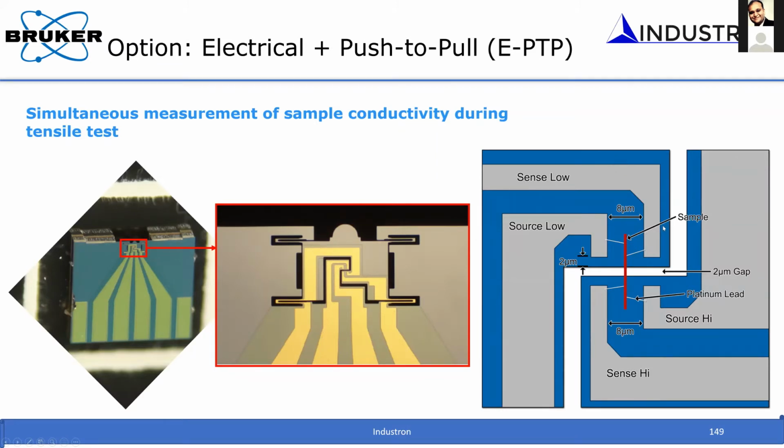For example, we have the PTP, basically an electrical PTP device, where you can put a nanoscale nanowire and connect it with these 4 probes, and we have fixed gaps. We know what the gaps are, and the 4 probes are very useful if you are trying to measure the resistance, because you need to null the resistance of the probes. That's why you use this 4 probe method. And using this technique, not only can you do mechanical deformation, but you can also electrically characterize it.